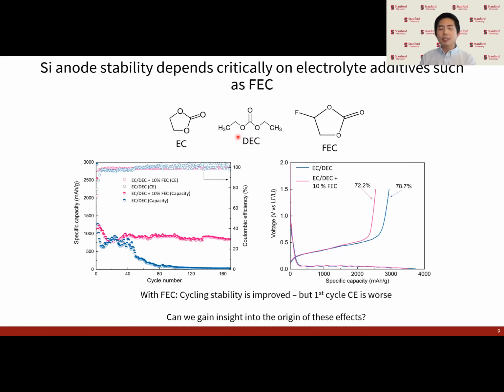But for silicon, there's an additional critical electrolyte additive, and that's a fluorinated ethylene carbonate, or FEC. And it's widely known in the field that with the addition of this FEC additive, so here this is with the addition of 10% FEC electrolyte additive, the capacity retention, so this curve down here, of the silicon anode and its lifetime is greatly extended. But at the same time, the first cycle efficiency of the silicon anode, which measures the amount of lithium you can insert into the structure and then retrieve back on the delithiation half cycle, decreases when FEC is added.